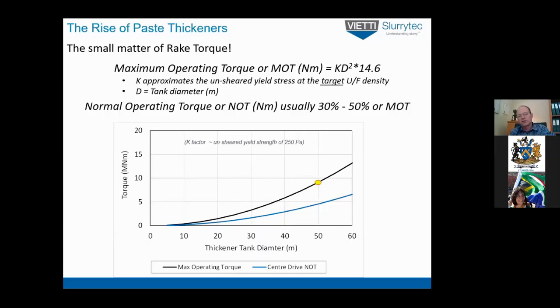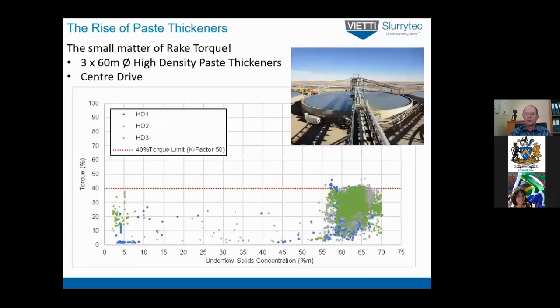So this is for a central drive. That blue line is for a typical central drive. But on a peripheral drive, you can almost run at 100% because the stresses are so much less as you drive it from the periphery. So it's very important to start looking at peripheral drives again. And just to bring this fact home,